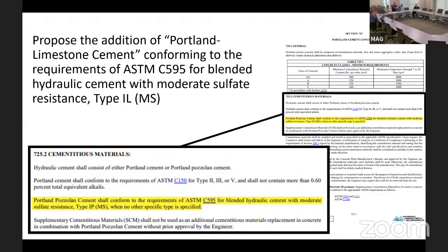In the top left corner, this is our proposed verbiage. Proposed is the addition of Portland limestone cement conforming to the requirements of ASTM C595 for blended hydraulic cement with moderate sulfate resistance, and that would be considered a type 1L MS.